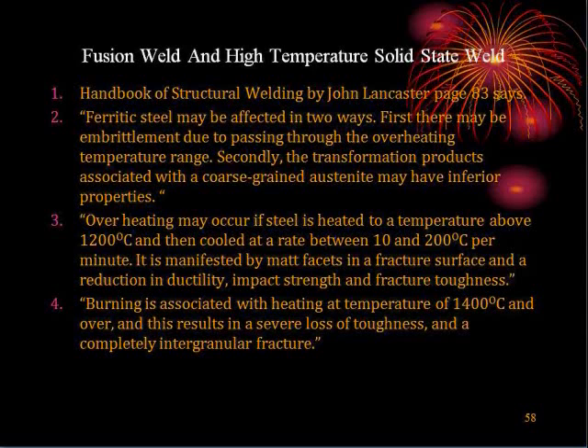Overheating may occur if steel is heated to a temperature above 1200 degrees C and then cooled at a rate between 10 to 200 degrees C per minute. It is manifested by matte facets in the fracture surface and a reduction in ductility, impact strength and fracture toughness. Burning is associated with heating at a temperature of 1400 degrees C and over, and this results in severe loss of toughness and a completely intergranular fracture.